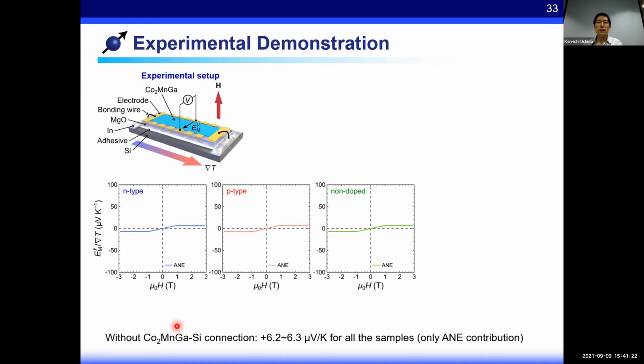To experimentally demonstrate the colossal transverse thermoelectric generation, we performed the thermal power measurement using an epitaxial Co2MnGa film fixed on various silicon substrates. The CMG film and the silicon substrate were separated by an insulating MgO substrate, and can be connected electrically only around the ends of the sample. Here we show the magnetic field dependence of the thermal power without the electrical connection. It's natural that only the anomalous Nernst effect was observed in this setup, and the result was irrelevant to the carrier type of the silicon substrate. Here we used N-type silicon, P-type silicon, and non-doped silicon.